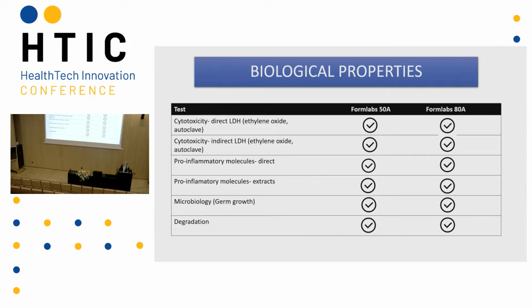We also investigated biological properties of the material in biolabs. I'm not showing here all the results because there is a huge number of them. Here is only the summary. Here you can see that we got very good, promising results. It proves that we can use these materials for reusable surgical instruments. We tested cytotoxicity on LDH in direct and indirect contact. We also considered two different ways of sterilization, low temperature and autoclaving. We also tested pro-inflammatory molecules, and we also did microbiological testing. We confirmed that there was no germ growth on the tested surfaces, and we also performed a degradation study in simulated body fluids.